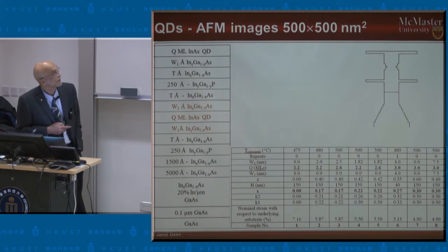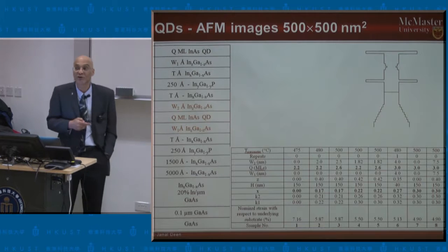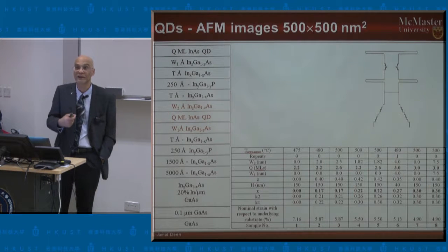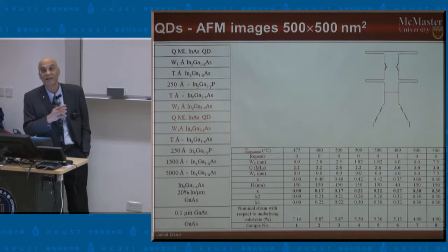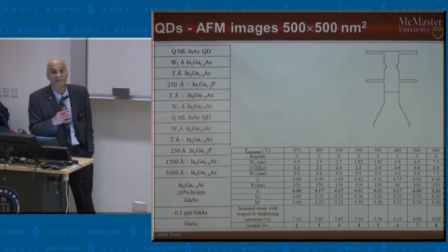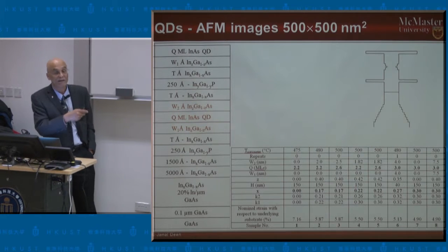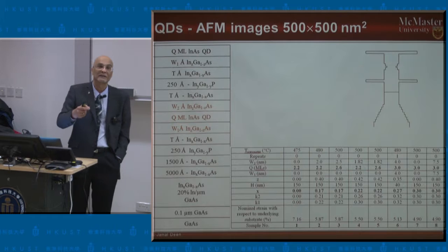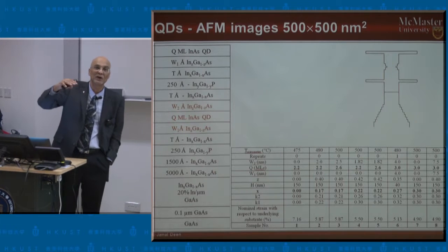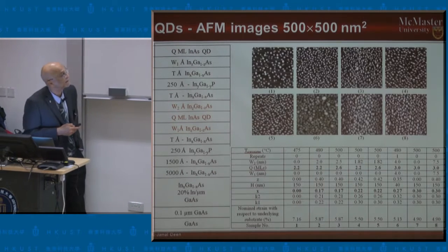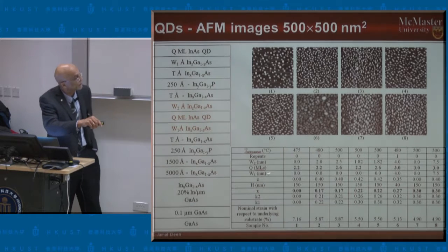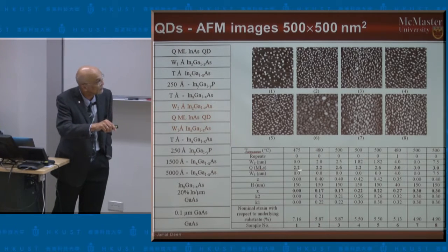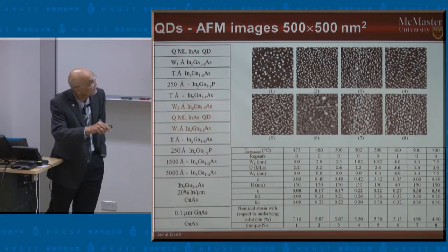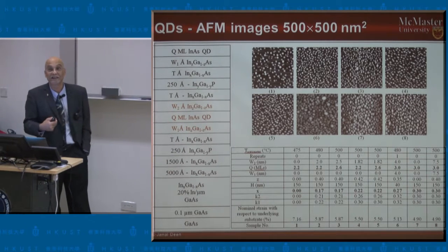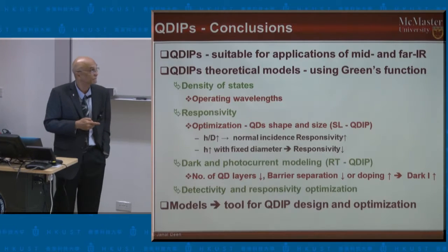We can also look at what happens if we apply strain to the device. So strain is a common technique that is used to actually tweak the wavelength response if we want to extend it between the physical phenomena that I showed you between bound to bound or bound to continuum transitions. This is an example of where we changed the number of quantum dot monolayers from 2.2 to 3.0. So you can see the density is changing, and in this way we can change the response of the device.